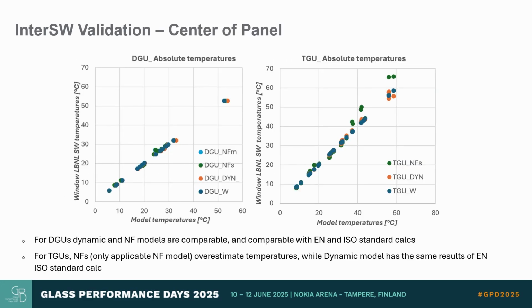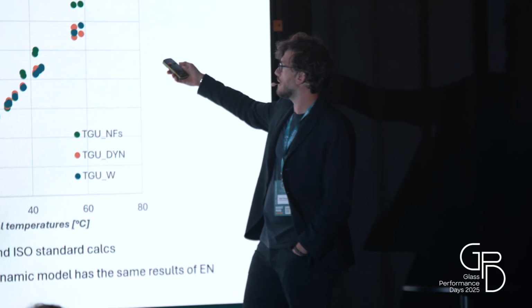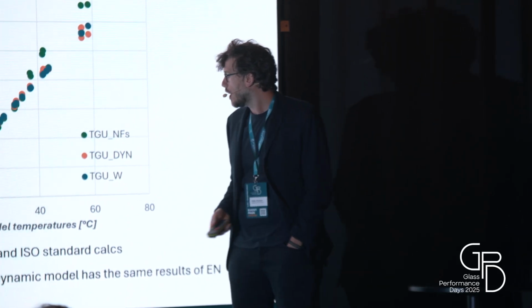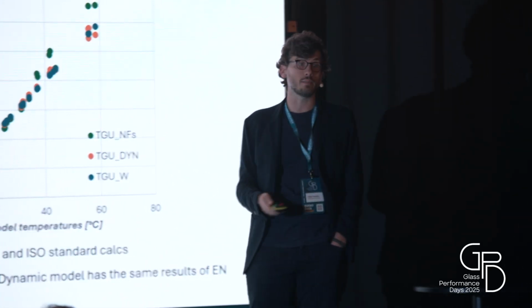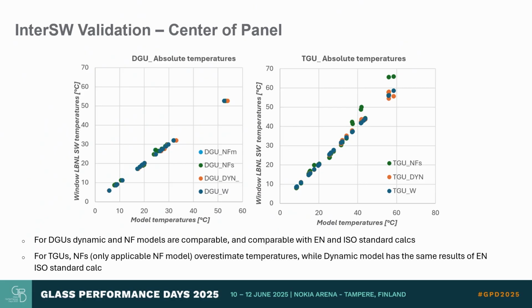So these are the results from the comparison with Windows software, and the closer you are to the bisectrix, here you have the temperature of the window, here you have the temperature of the different models. So if you are exactly on the bisectrix, of course you have the same results. And what you can see is that there is an overestimation of the temperature, especially in the triple glazing unit, when it comes to the NF models, while our model is basically very close to the Windows results. That's for center of panel.